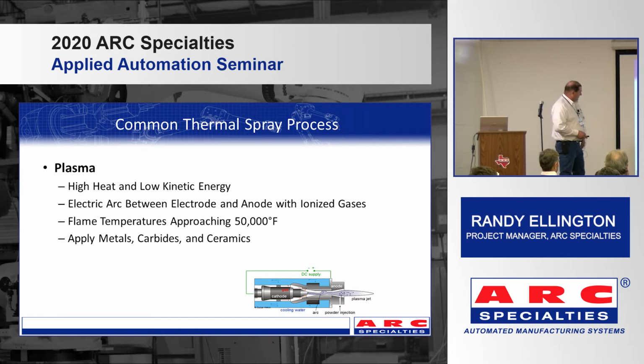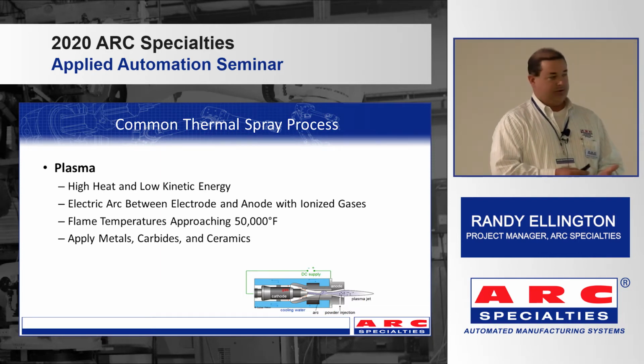Next process, plasma. High heat. Again, it's relative. It's compared to the other, it's much higher. You can get temperatures up to 50,000 degrees Fahrenheit. Why is that important? Ceramics. They use them for dielectric properties, seal surfaces.